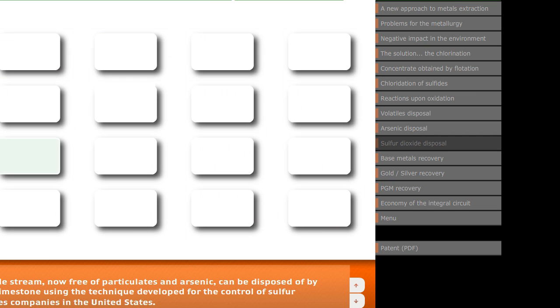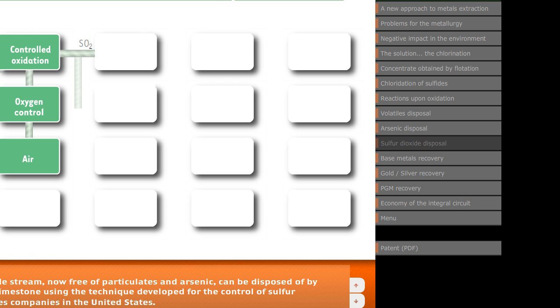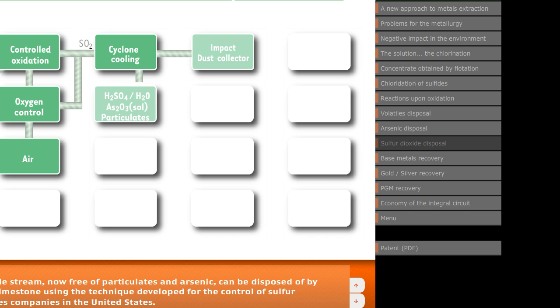The sulfur dioxide stream, now free of particulates and arsenic, can be disposed of by scrubbing with limestone using the technique developed for the control of sulfur dioxide in utilities companies in the United States. This well-proven technology, practiced on a very large scale, consists of scrubbing the gas stream with a slurry of limestone. The resulting calcium sulfite is oxidized in situ to hydrated calcium sulfate or gypsum.